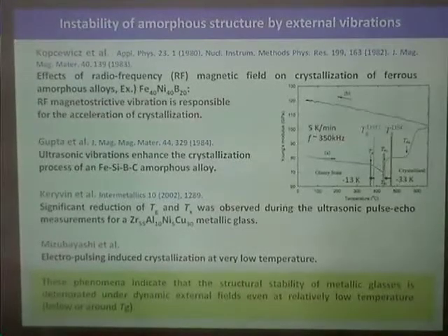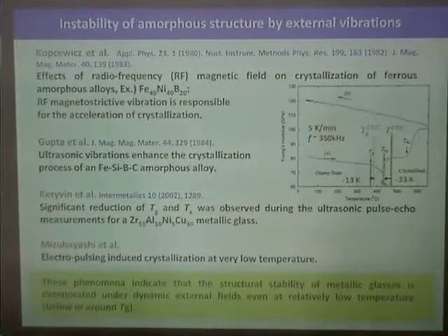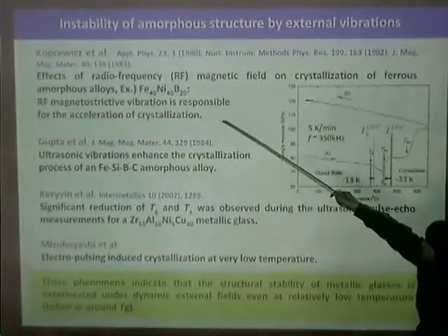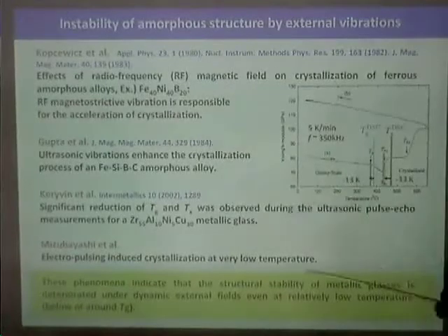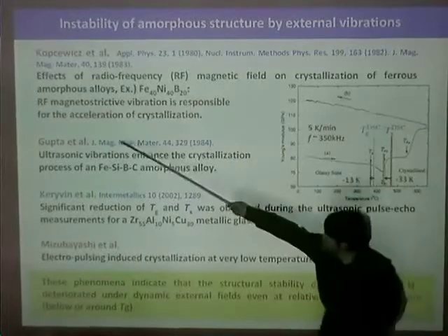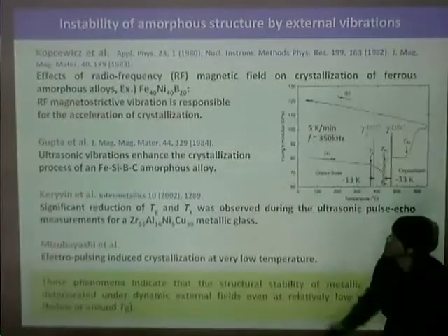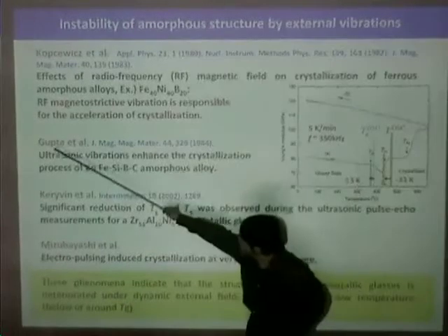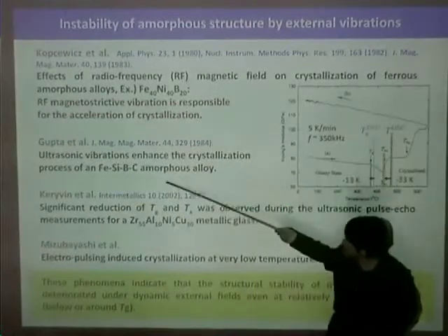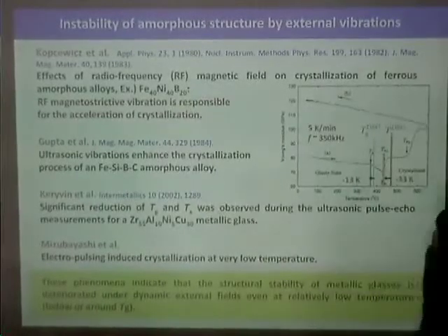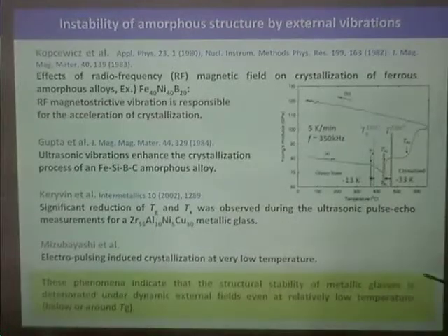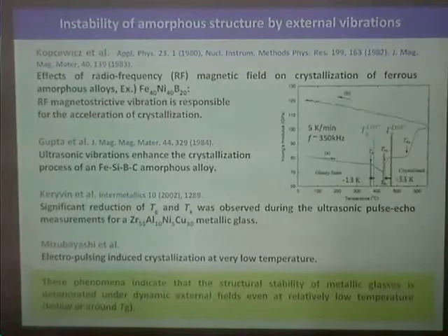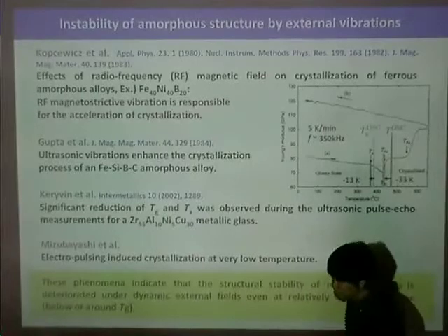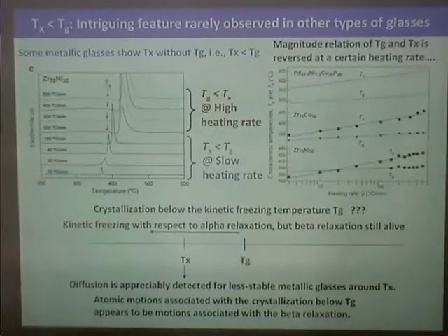Some other researchers have reported similar results. In the case of Kopcewicz, he proposed the effect of the radio frequency magnetic field on the crystallization of the ferrous magnet. So radio frequency magnetostrictive vibration is responsible for the acceleration of the crystallization. For example, Gupta reported that ultrasonic vibration enhances the crystallization of iron-based amorphous alloys. So these phenomena indicate that the structural stability of metallic glasses is deteriorated under dynamic external fields, even at relatively low temperature, below the glass transition temperature. So this is one topic of my talk.